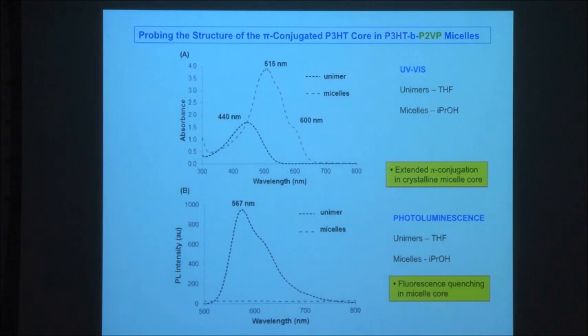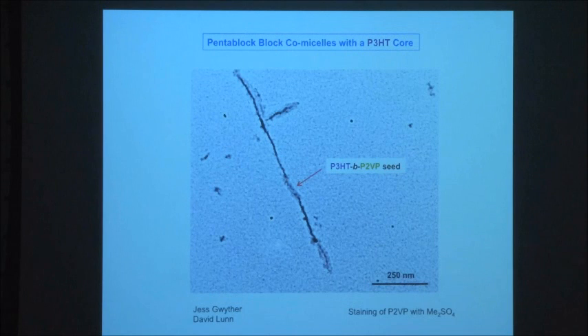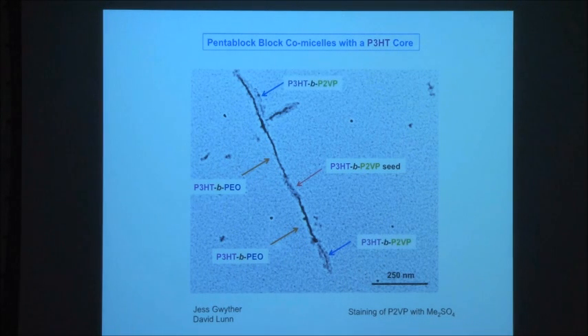So very recently, we've been able to make the first examples of block co-micelles from poly-3-hexylthiophene. We started with a seed. This is the seed we started with, which is P3HT-b-P2VP. You can add to that P3HT-polyethylene oxide, so this grows off the end, and then you can add more P3HT-b-P2VP so that you can make pentablocks.